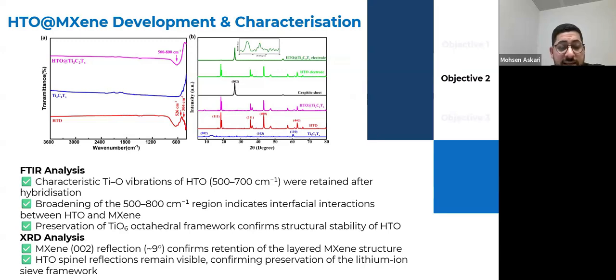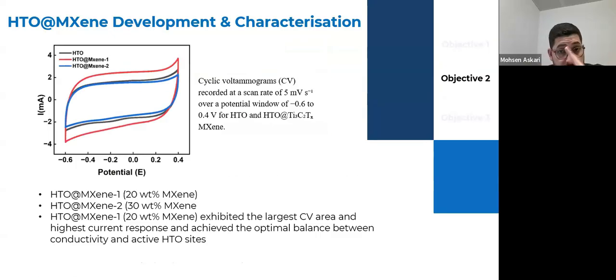For XRD analysis, the MXene reflection at 9 degrees confirmed retention of the layered MXene structure, and the HTO spinel reflections remain visible, confirming preservation of the lithium ion sieve framework after making the electrode. And based on the cyclic voltammetry test, we optimized the amount of MXene, because when MXene increased to more than 20%, the CV area decreased. It shows the conductivity should be optimized, and 20% MXene has the highest current response and achieves the optimal balance between conductivity and active HTO sites.